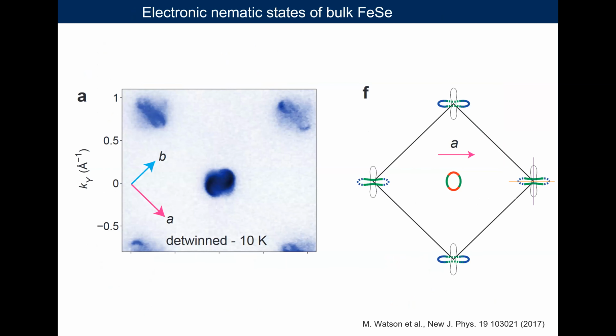When we go through a nematic transition, the system potentially could also form twins. And in order to avoid this, one has to apply a small amount of strain, which was done in this experiment, to be able to see the precise Fermi surface. By detwinning the sample, it was established that the hole pockets elongate along one direction and the electron pockets along the other direction. So we have a momentum-dependent change in the way the Fermi surface elongates as a function of applied strain.